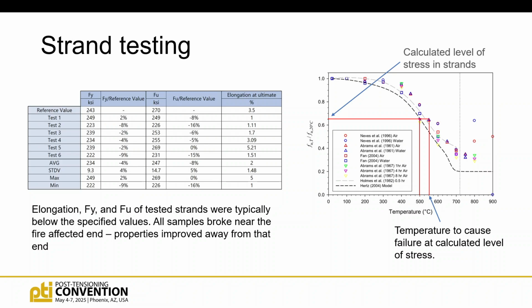And so you can see here, we had a couple of them that were fairly low. This test 2 was really close to one of the fire locations. But all in all, the strand ultimate strength wasn't that bad.